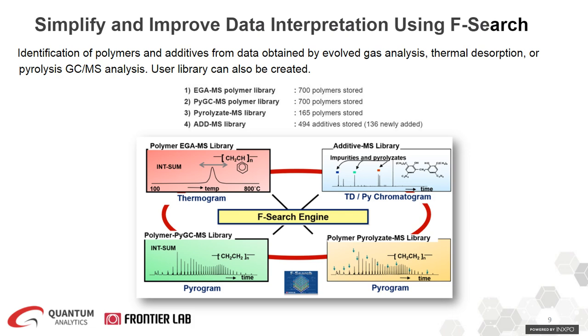So let's see how we can analyze these compounds and fragmentation in Pyrolysis-GC. As shown here, F-Search is a search engine that has 4 unique interpretation libraries. So you can identify additives, volatiles, lighter components, as well as oligomers, heavier, and polymeric compounds. F-Search also allows you to create your own user library, so you could perform contamination analysis, comparison, and also failure analysis. F-Search has other features like the ability to overlay different chromatograms, extract different m/z ions, and also perform integrated sum analysis, which in this case, the F-Search engine can actually integrate the whole chromatogram, make an average mass spectrum, and then identify the corresponding polymer.